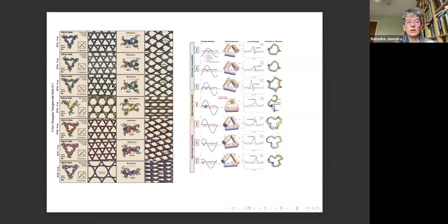You design it in a specific manner. So this hairpin can, by introducing a new strand, open up and expand the structure, or take the strand out and close it up. The hairpin will shrink the structure. That theoretically can be done.